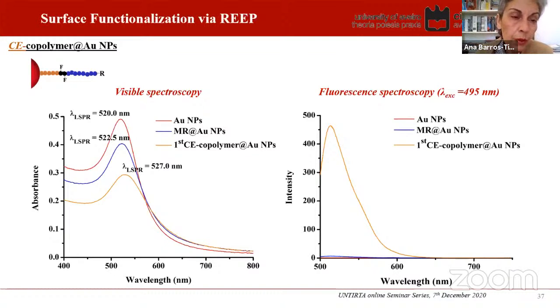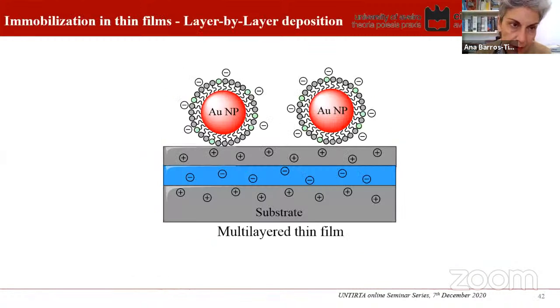But the idea was to combine this fluorophore with the biotin and use all of that as biosensing materials. But the results weren't as straightforward as one would expect because of the reaction conditions involved, namely the polymerization. But that we can discuss later. Finally, having prepared these gold nanoparticles, but they are in the colloidal form, to use them as a biosensor, ideally one should try to immobilize them so that the use of the biosensor is more practical. So we tried that using the layer by layer deposition and studied that.